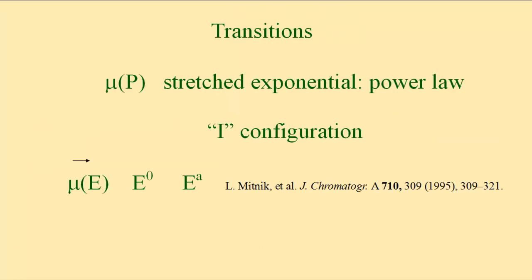There are transitions that are apparent in experimental measurements. First, the electrophoretic mobility does depend on the probe size. It does so through a stretched exponential for smaller probes, a power law for larger probes, with a sharp transition probe size between them. Note, by the way, the fact that we can say this is a stretched exponential, not a power law, or this is a power law, not a stretched exponential, means that we can tell the two of them apart using our numerical methods.